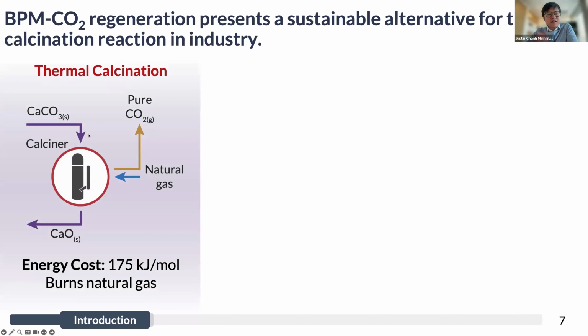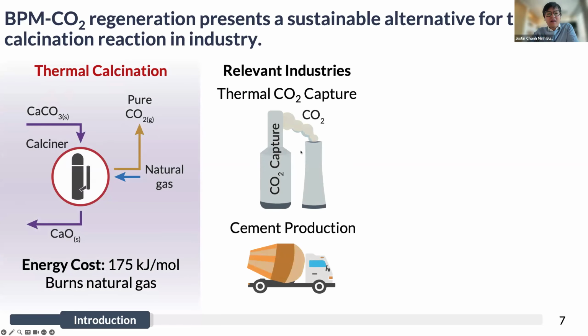So this calcination reaction is really important for carbon capture and also for a lot of industries like cement production. Essentially, you take a calcium carbonate solution and you burn it at very, very high temperatures using natural gas, and that allows you to liberate carbon dioxide from that calciner. This is really important because when we capture CO2, we often capture CO2 in the form of a carbonate, and then also in the production of cement, we have to take lime and convert it into cement clinker precursors, which